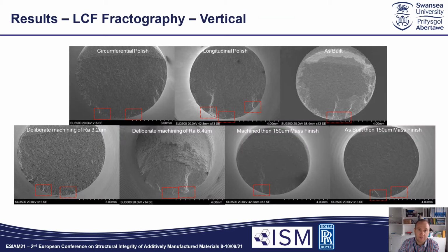A quick look at some of the fracture surfaces, and given here are the fracture surfaces for the vertical specimens. Despite the change in surface finish, there's not a massive difference in the nature of the fracture modes. The reason for this is also strongly attributed to the loading ratio of -1, which of course introduces a compressive portion to the fatigue cycle, which can effectively eradicate many indicative fatigue features on the surface, such as striations and